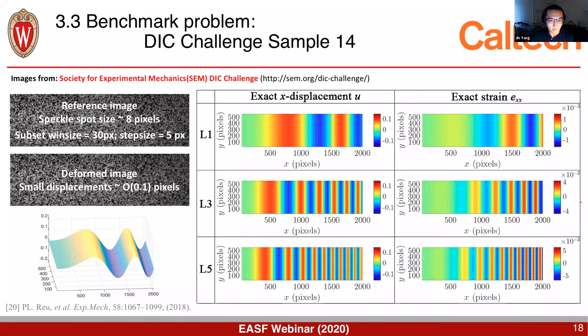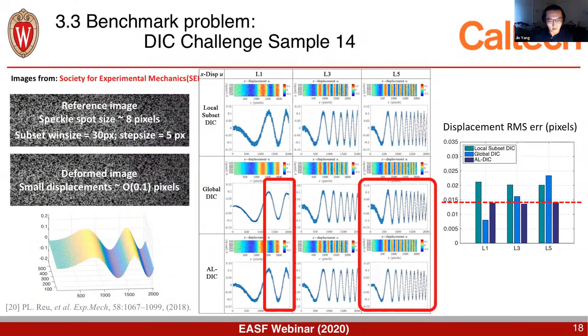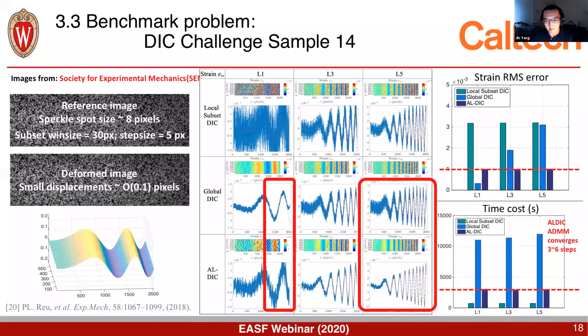One example solves DIC Challenge Sample 14 — a highly oscillating deformation field with a sine function of changing frequency. Comparing local, global, and AL methods: the local method always has the largest noise. For smooth deformation, the global method with suitable regularization provides good results, but may have boundary bias error. AL has no boundary bias error and provides very good results for heterogeneous deformation. Overall, the root mean square error for the displacement field is best for AL among all three methods, and similarly for the strain field — particularly for highly oscillating strain fields.